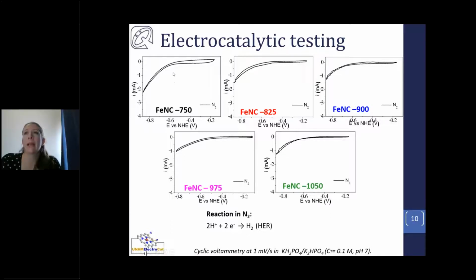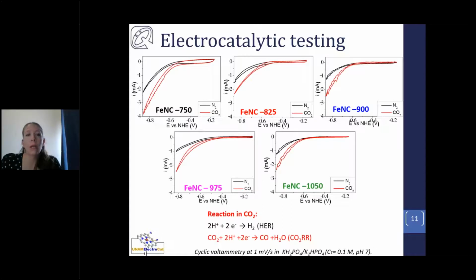We also see that the catalyst prepared at the lowest temperature has the lowest activity. And then there is a decrease, sorry, it has the highest activity. So we have the highest current when we prepare the catalyst at a lower temperature. This is attributed to the fact that we have a higher surface area, resulting in more activity. Once we bubble CO2 to our electrolyte, we see an increased current. And this increase in current is correlated to the reduction of CO2. So we see that all of our catalysts are actually reducing CO2, but they're also having some current that can be attributed to the hydrogen evolution reaction. We also see that the catalyst prepared at the lowest temperature is the most active, whereas there is a slight decrease at higher temperatures.